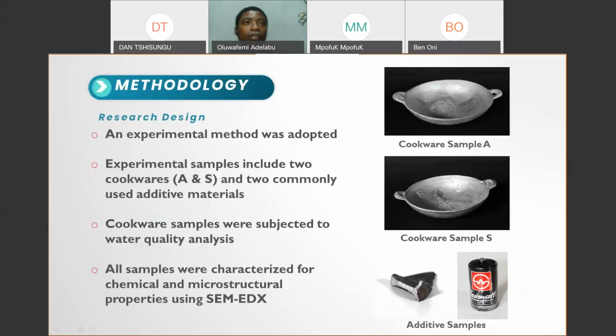So in this study, we adopted an experimental method, and we selected experimental samples from cookware: two cookware samples that were specially prepared, and two commonly used additive materials. The cookware samples were subjected to water quality analysis, while all the samples were characterized for chemical and microstructural properties using SEM EDX.